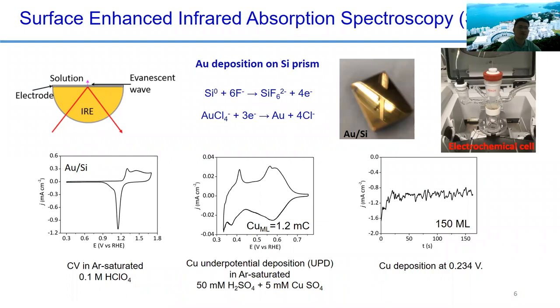So when the infrared beam passes through this electrolyte and reflects on the working electrode, it can then be collected by the detector. So the infrared can only pass through this very thin layer, so the impact of the water will be minimized. But still, a significant amount of water could absorb the infrared signal. So usually the spectrum is quite ugly, and if the signal of the reaction intermediates is weak, we cannot see this kind of signal on the infrared spectrum. So we use this surface enhanced infrared.